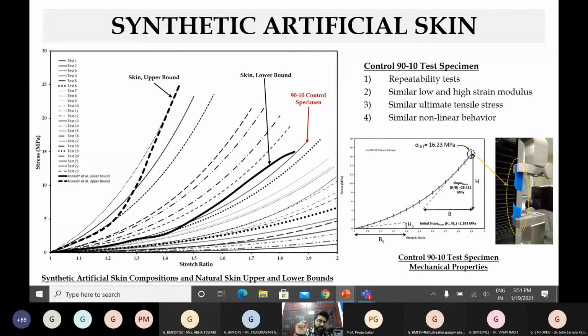So what we do is, step one is we do a bunch of tests with different compositions. So all this plots in this graph, you're looking at this bunch of tests, which is going from a very compliant or non-stiff material composition to a highly stiff material composition. So we have gone all the way from the bottom to the high one. Wherever the composition or the hardness is low, that is the lower side. And on the higher side, we are looking at a much stiffer curve of stress stretch.